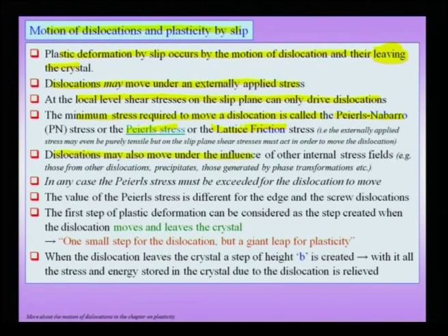Dislocations may also move under the influence of other internal stress fields, like for instance those arising from other dislocations, those arising from coherent precipitates, those arising due to phase transformation, those arising due to thermal mismatch at interfaces, etcetera. So, the internal stresses may also be responsible for moving dislocations. But in any case, the Peierls stress must be exceeded if slip has to be initiated at the microscopic scale.